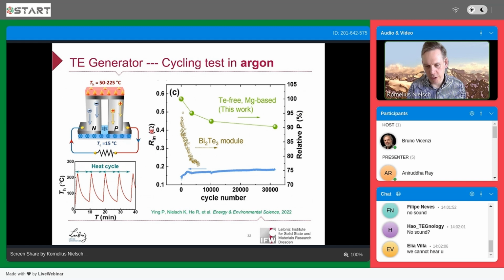One of the strategies to test the performance of this device is to measure the internal resistance. And you can see here, if you apply, for example, 30,000 of these heat cycles to these devices, the internal resistance is changing slightly, but it is rather stable in this device. If we compare it with a standard bismuth telluride module, this module is not capable of surviving this rather strong thermal shock. So it will die much earlier.